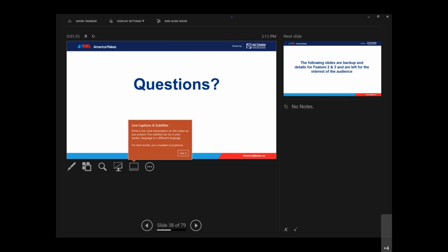All right, thank you. So let's see, we got a couple more here. Was the post-HIP aging completed in air, under hard vacuum, or an argon atmosphere? Again, Shomo. Yeah, so all of this was done in an argon atmosphere because we were doing it in post-aging. We were quenching at a faster rate, like air cooling, so we couldn't do it in a vacuum atmosphere. But we made sure that they were all done in argon atmosphere.